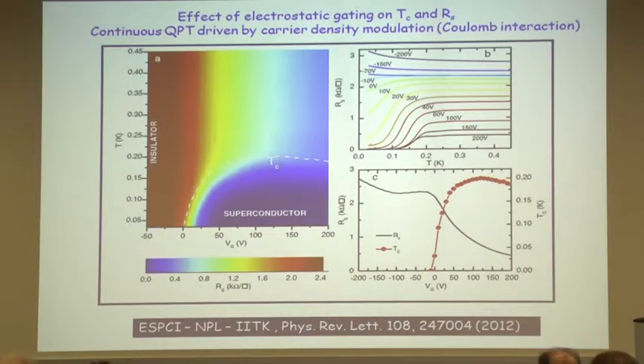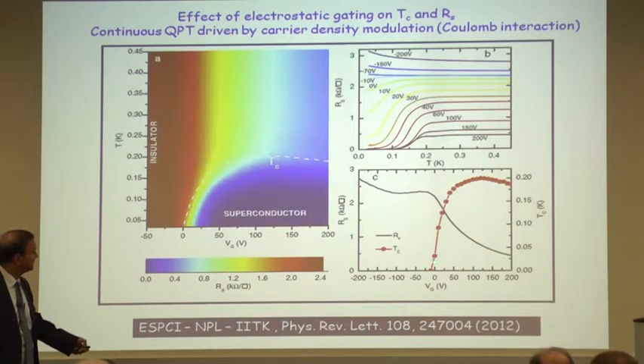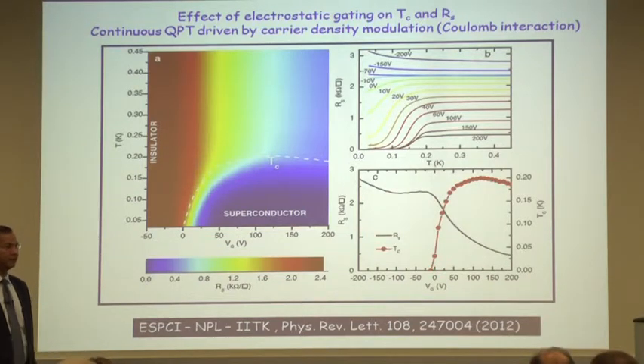And this also shows the behavior of sheet resistance. And one can plot sheet resistance versus TC. Again, you get another scale in the problem. So as you can see here, this is TC as a function of gate voltage. So at zero positive gate, it is going up like that. And the sheet resistance has a highly nonlinear behavior with respect to the gate voltage. It's not perfect, it's not linear. So the response on the negative side is very different from the response on the positive side.